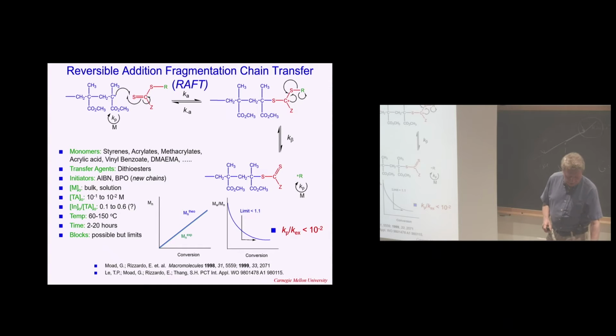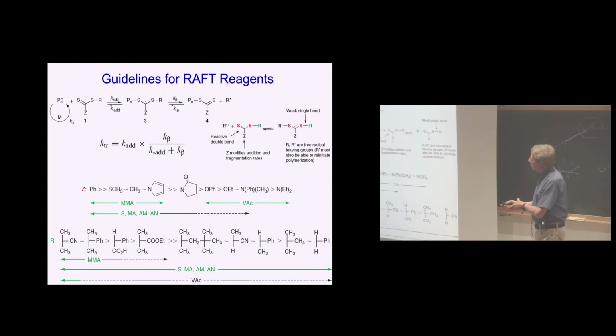So I will show you some examples of how to select a RAFT reagent, because what is important on one side is that this bond should be reactive, so it should be stabilized by this group Z, which are listed here. But also, once you add this radical, you don't want this persistent radical to be stabilized too much because it can terminate with another radical. So you want to fragment it, and the rate of fragmentation would depend on the leaving group ability. So from a point of view of stabilization, the phenyl group would be best, then trithiocarbonate, then some alkyl dithioesters, then xanthates, then dithiocarbamate. So this would depend on what kind of monomer you want to polymerize.